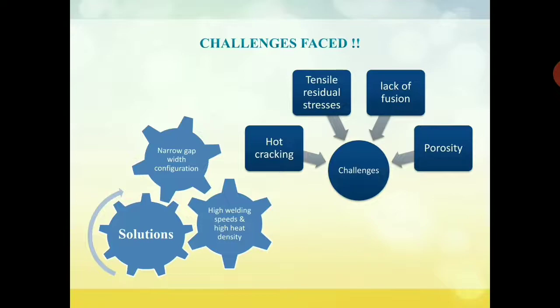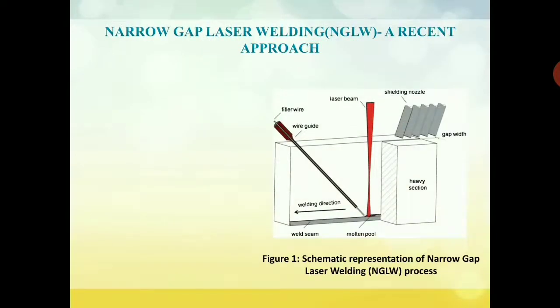To overcome these challenges, high welding speeds with high heat density and narrow gap width joint configuration must be implemented. Narrow gap laser welding promises to be a flexible process because here the laser beam is transmitted through an optical fiber to the inaccessible areas for fabrication of thick section steels. This multi-pass welding process contains an added filler whose function is to enhance the quality of the weld and also effectively tailor the microstructure and mechanical properties. A trailing shield gas like helium, argon, or nitrogen is also administered during the process to avoid atmospheric contamination.